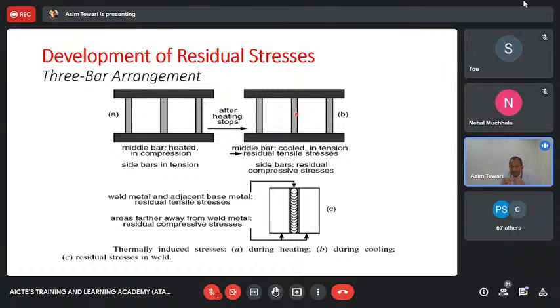So the center rod is now trying to expand, and because it's not being allowed to expand, it gets compressive residual stresses. The other 2 rods which are holding it back get the tensile residual stresses. So the center is in compression, these 2 side regions are in tension. Now you keep heating, so which means that this has a higher temperature than the sides because the heat source is centered. And that leads to eventual melting of the center part. And once this center rod melts, what happens? Initially, when you heated it up, it started expanding. Since it could not expand, it got constrained, and thus it developed compressive residual stresses.